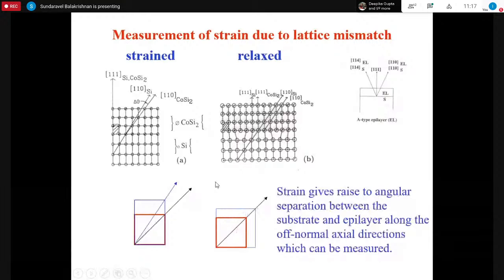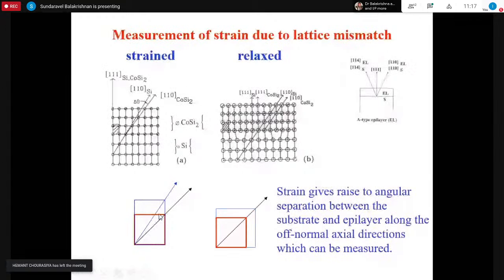And when you look at some off-normal axis, say the normal direction is 100 and the off-normal axis is say 110 at 45 degree, when you see both the signals from the substrate and this epilayer, they'll be showing the same orientation, same dip positions for this off-normal axis. Suppose it is strained with respect to the substrate, if the top layer is getting strained, then it will contract in X to match with the substrate, and to conserve the volume, it has to expand. When it is expanding, from the substrate you are getting the position here, and from the epilayer there is some lower angle. So by measuring this angle difference between substrate and the epilayer, you can find how